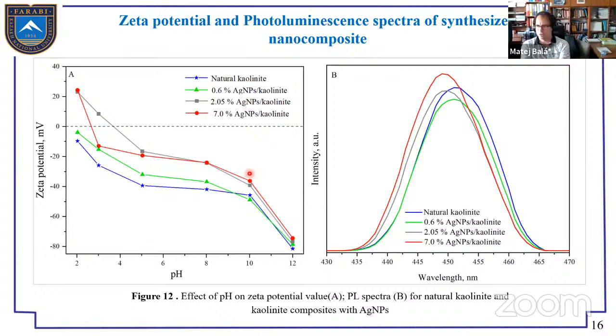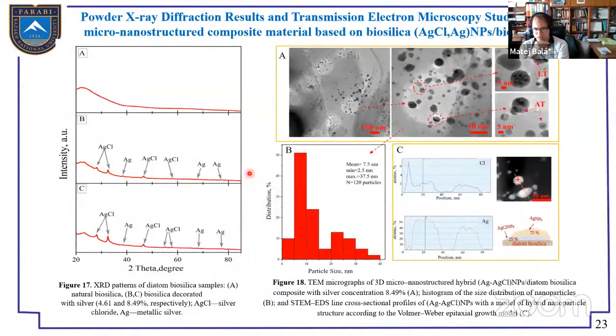Okay, and then if you can go to slide 23, actually this part of the work I think is very interesting, also with this kind of layered structure that you have, silver chloride and then silver nanoparticles on that. But I would like to ask about part C of this picture on the right, the TEM analysis. I am not very familiar with these graphs where you have the position and atomic percent. It may be a simple question, but I can see that for chlorine there is a peak around 10 nanometers, the highest peak is there, and for silver in this region there is a value close to 0. So what does it mean?